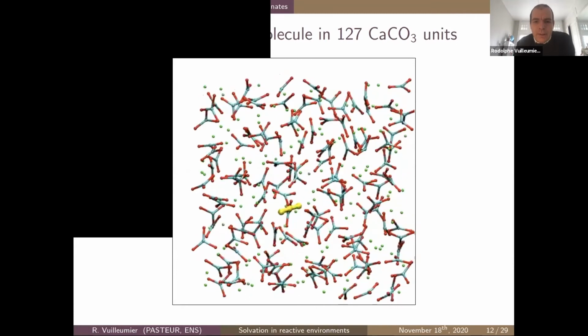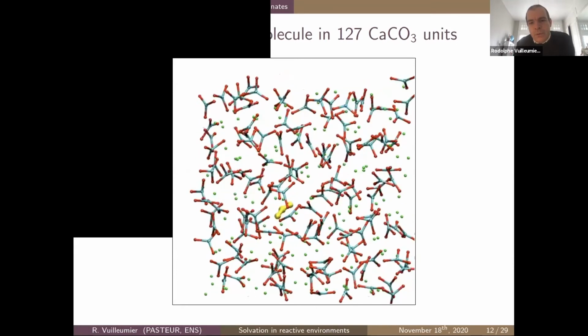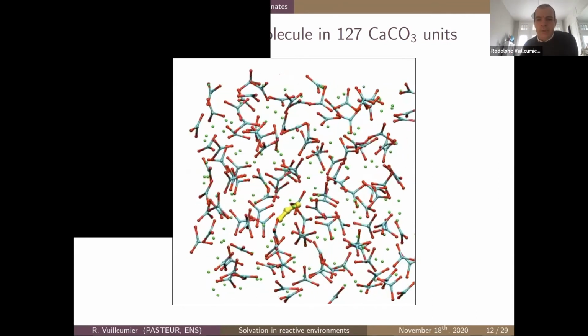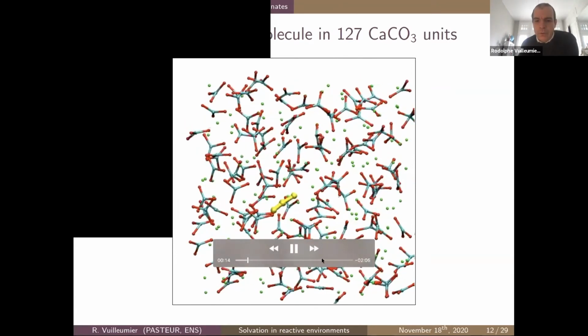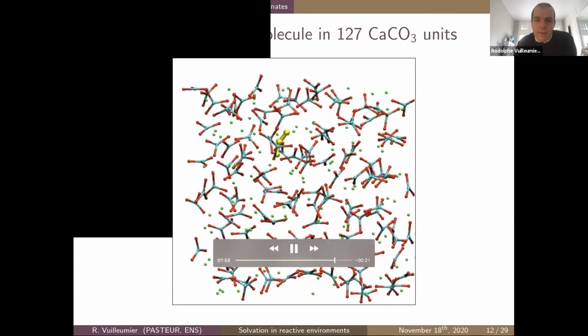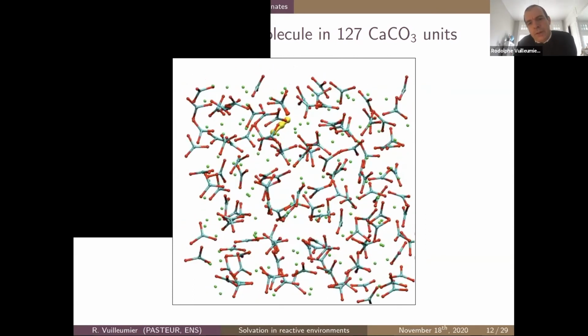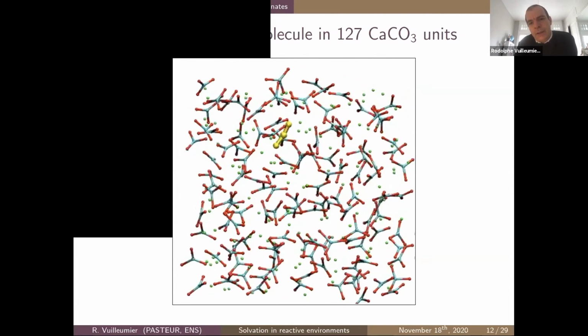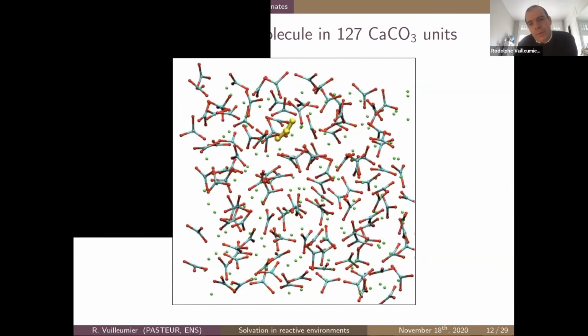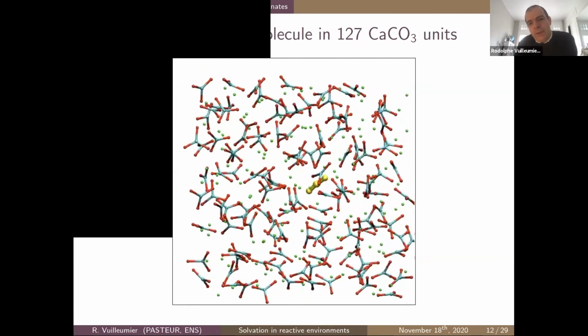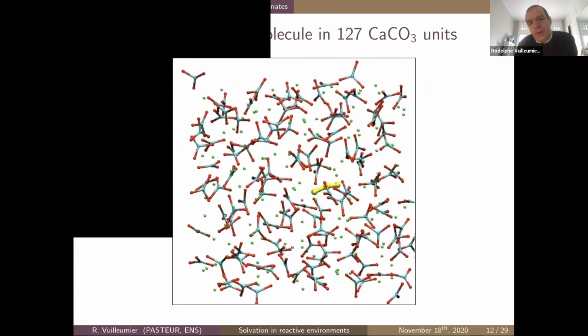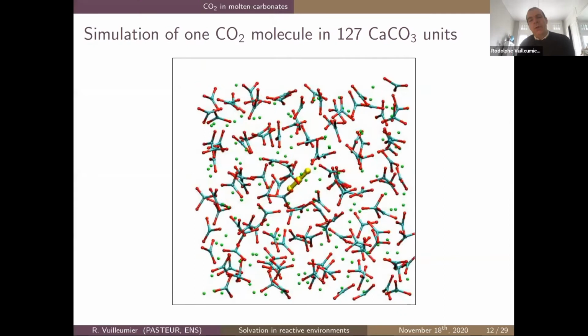And here's a movie from the first principle MD, and we see that CO2 reacts with the carbonate itself. We see here a reaction of CO2 with carbonate to form another CO2 with a carbonate behind. Now, if I go much further, maybe somewhere here, sorry, what we see is that we have transport of CO2 through a series of these exchange reactions with a neighboring carbonate. In purple we have some kind of reaction intermediate, and then we have transport of the yellow CO2 quite far in the cell, while we have little displacement of the atoms. It actually diffuses through these hops.